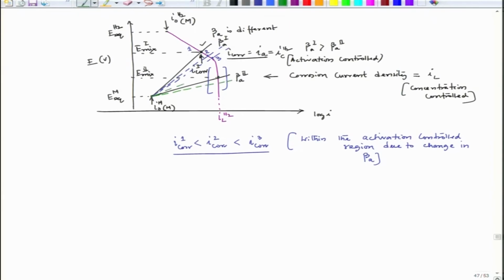This is one change, there could be little increase in the change. So, here I could have situations like 4, 5, 6. Now, in this situation if I try to see the corrosion rate of that metal, this is i_corr 4 equal to i_corr 5 equal to i_corr 6, since all are equal to i_limiting. And in all cases, corresponding i_corr 1 is less than i_corr 2 less than i_corr 3.